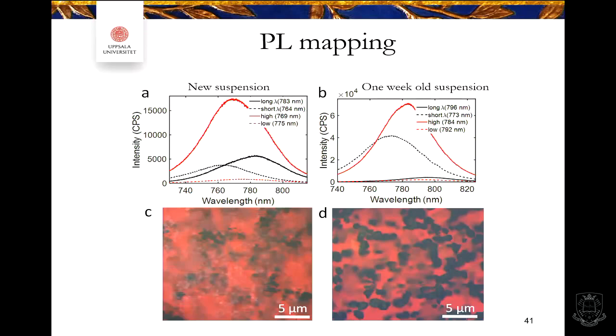Here was also a comparison between a new suspension and a 1 week old suspension, and this is photoluminescence mapping of the crystals. And we could also see that the peak position and the intensity varied a lot also. Here you can see the intensity in photoluminescence emission.